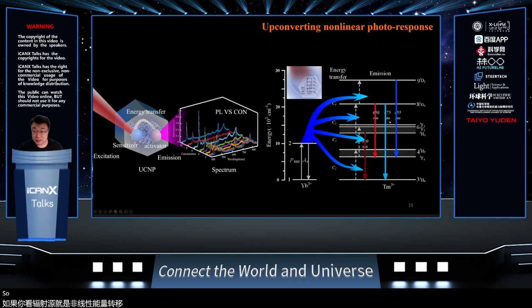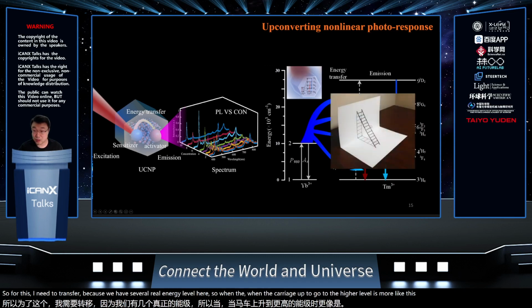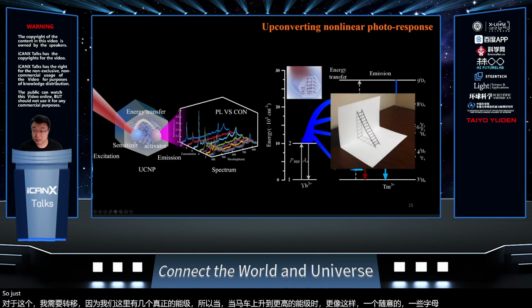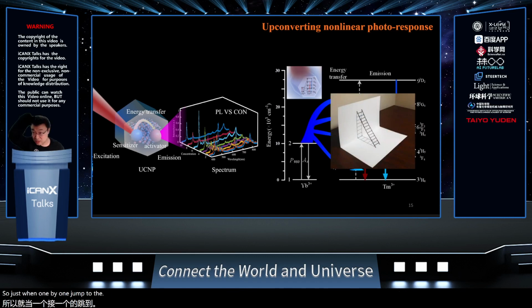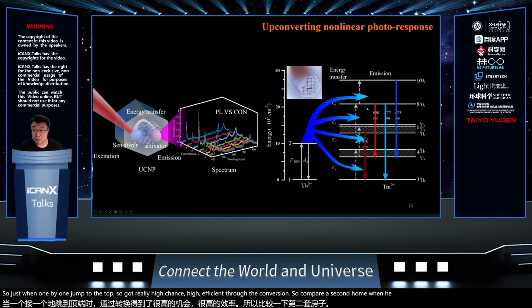For this energy transfer, because we have several real energy levels here, when the carrier goes to the higher level, it's more like climbing a ladder. Just going one by one, jumping to the top, so there's a really high chance, a highly efficient conversion. So compared with second harmonic generation or two-photon absorption, this material has a much higher conversion rate.